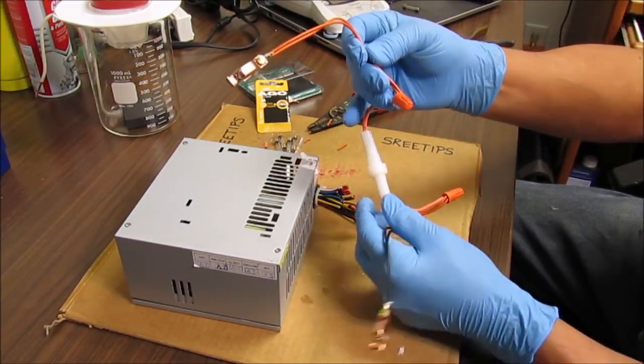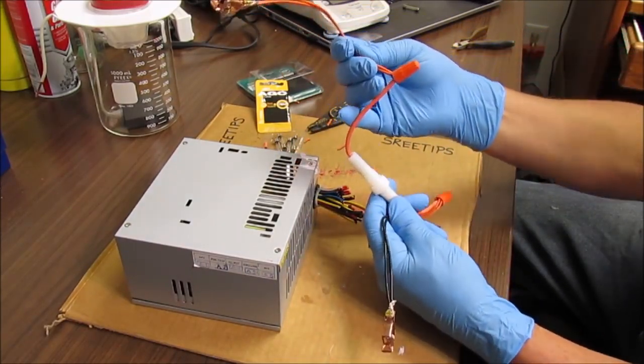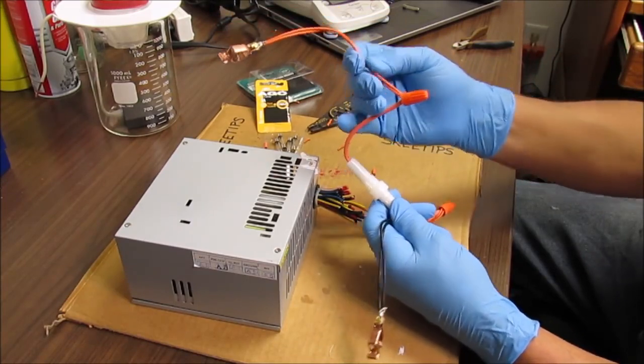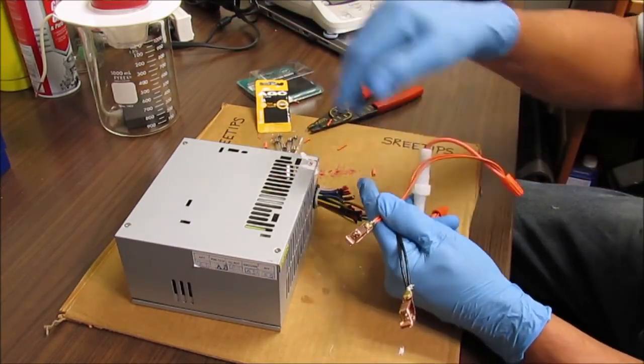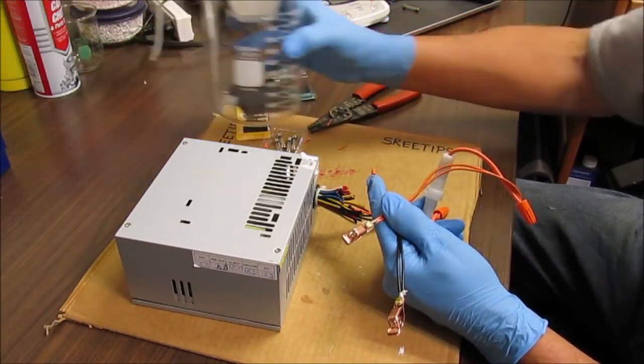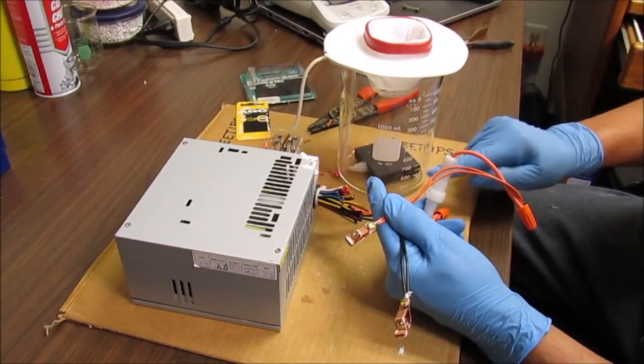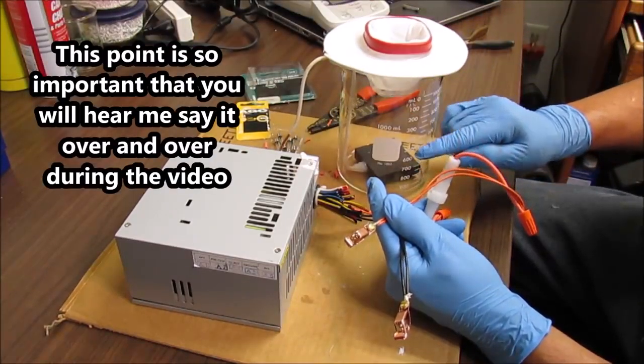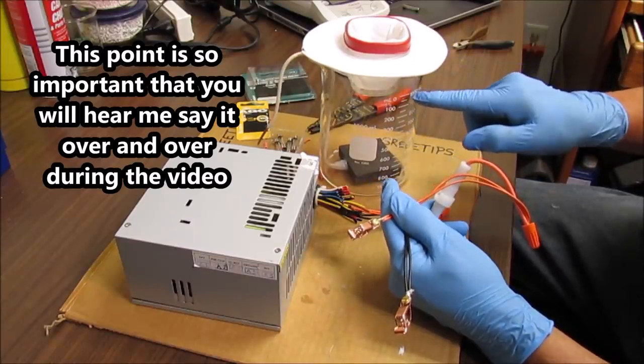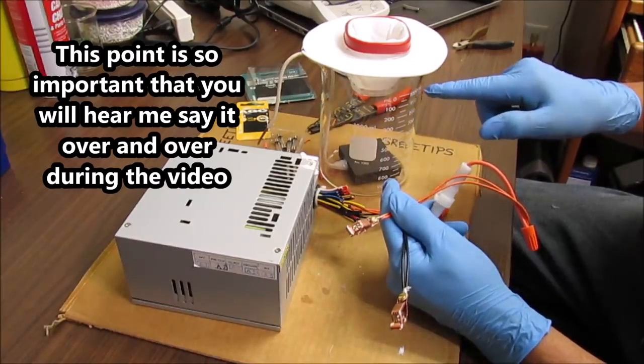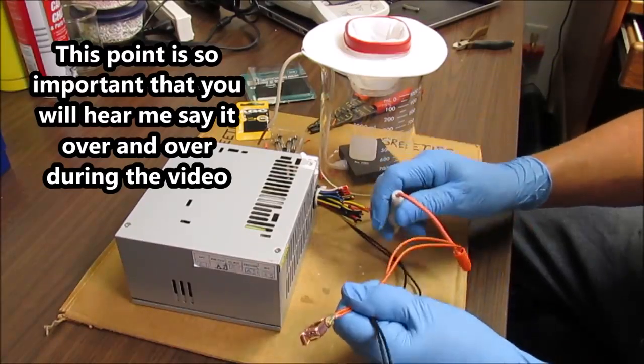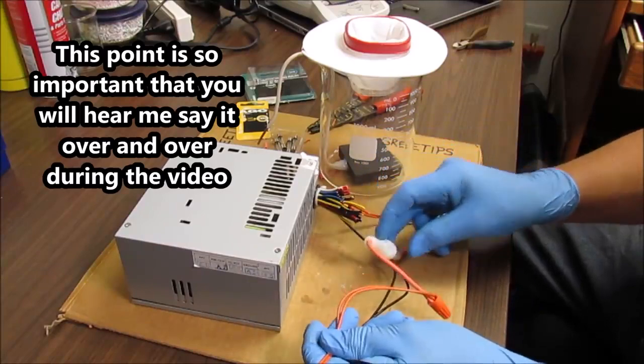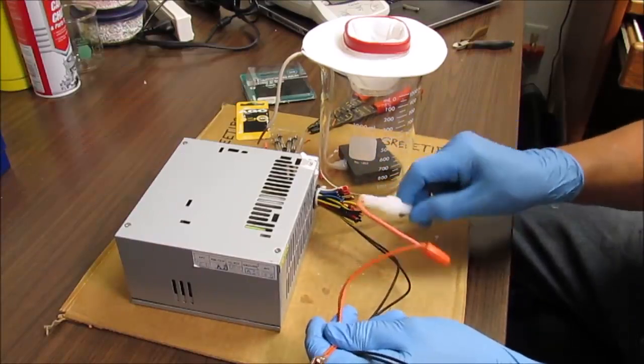Okay, what this inline fuse will do for me is, as the silver crystal grows in the silver cell, it will start to grow upward in the cell. If it makes contact with the anode basket and burns through the anode bag, then the amperage will immediately rise and blow this fuse and save my batch of pure silver crystal.